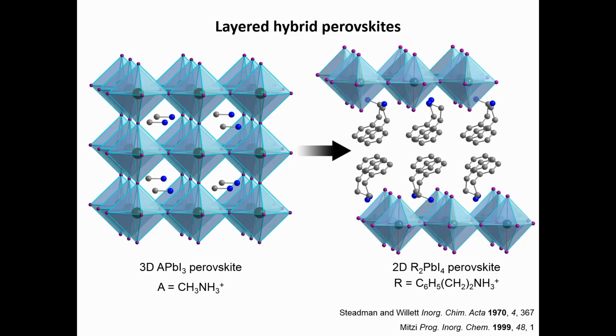So we found a composition that was a white light emitting perovskite, and we could do a very slow crystallization. When you slow down the crystallization, the precursors have a chance to come together, fall apart, come together, fall apart, and that corrects any defects you form in the crystal. And you can make really nice big crystals.